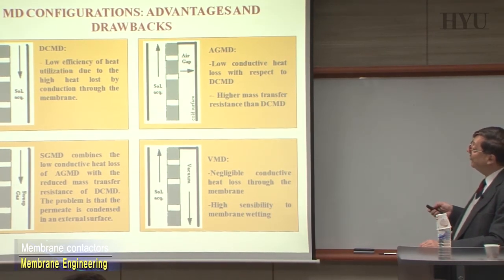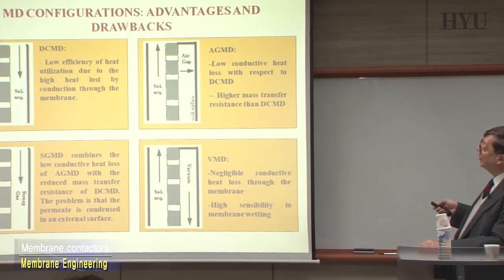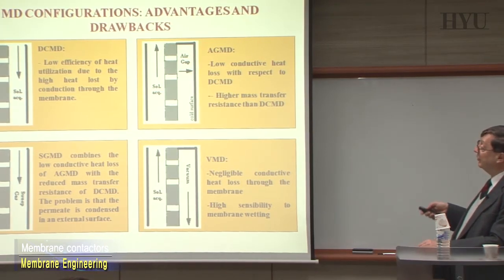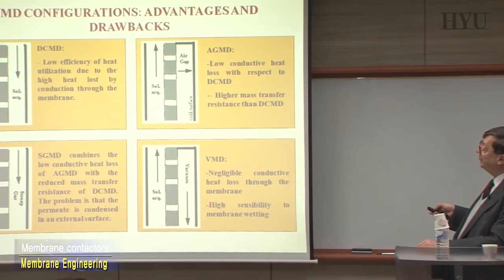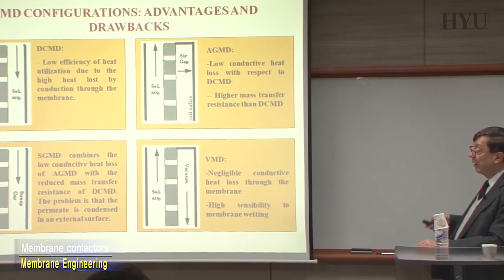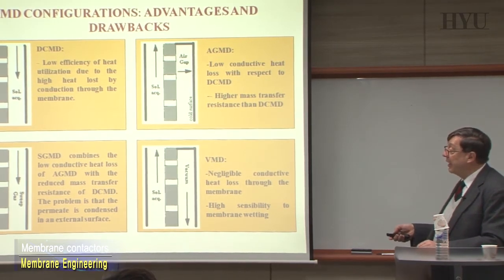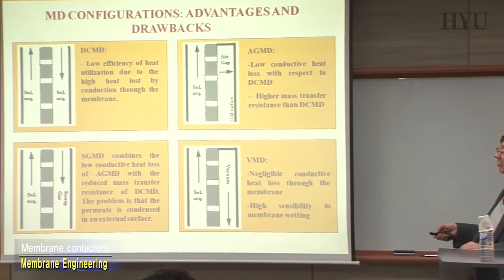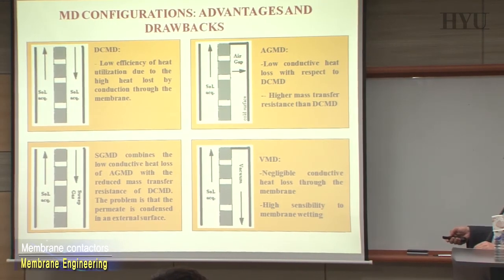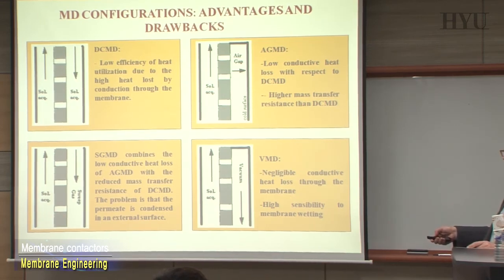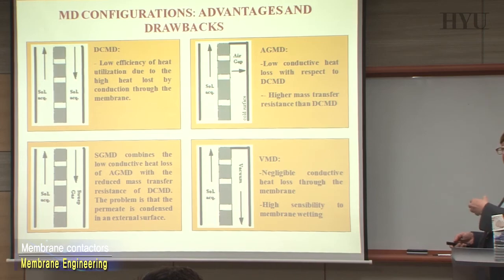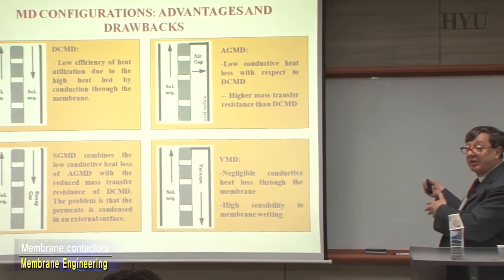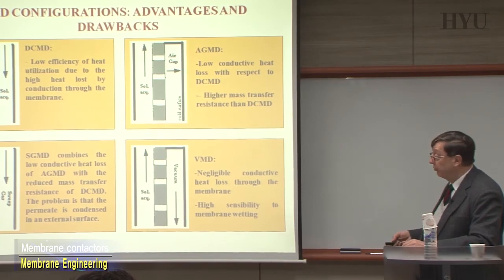In air gap membrane distillation, again, you have a low conductive heat loss with respect to the direct contact, so this is an advantage, but you have a higher mass transfer resistance than in DCMD. For what concerns the sweeping gas, you combine low conductive heat loss with a reduced mass transfer resistance. What is happening here is that the permeate is condensed on an external surface. You have a certain distance between the membrane and the plate in which the condensation takes place, and afterwards you have to remove and recollect it, and that is a cost that you have to consider.